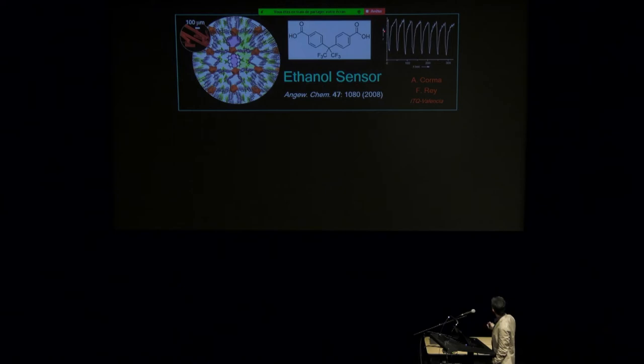So if you measure fluorescence as a function of time, and you pass a current wet with alcohol, ethanol, fluorescence goes down. And then if you pass a current dry, it goes up, and down and so on. So there's a repeatability, and the response is a matter of seconds. So this shows we have an ethanol sensor. This was work done in collaboration with Avelino Corma and Fernando Rey in Valencia.